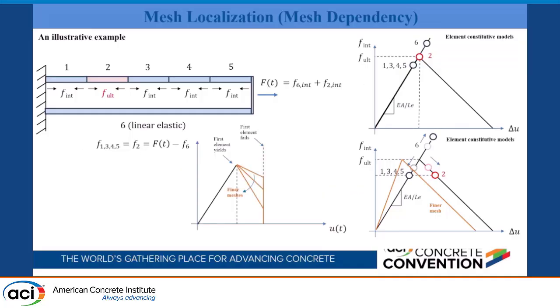And this will manifest itself if I subtract that bottom curve from the top backbone curve. This is the effective forces that are being transmitted through the upper chord. And now you're seeing, as you refine the mesh, a softening response. So the response is not unique. As you refine the mesh, you're going to get softer and softer post-peak responses. And in this particular problem, this may not be an issue because you know the physics of this problem. It's easy to understand what's going on. You may not even need to do an analysis here. But imagine that this is a part of your structure in a huge structure, and this is a problematic corner of it. Now the load redistribution is all messed up.